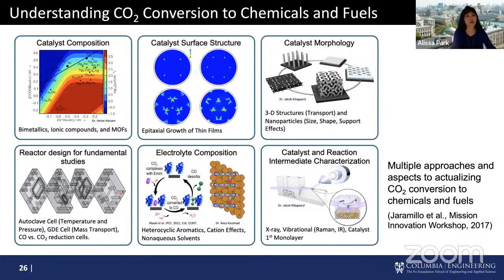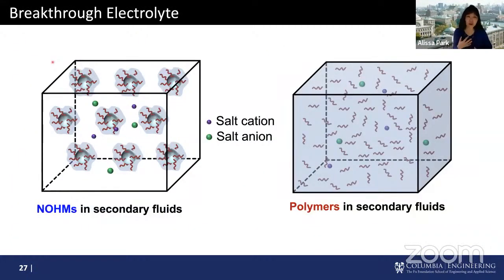catalyst. A lot of my colleagues are working in this area, looking at how to develop new catalysts, catalyst morphology, even reactor systems. But not that many people really focused on electrolyte design. In fact, the CO2 solubility in regular conventional electrolyte is very low. So then you can go to 2 different options. Either you can go to gas diffusion electrode, minimizing all the dissolution issues, or you can make the electrolyte better, increase the solubility of carbon dioxide. That led me to think about what if we use this NOHMs system we developed as additives for electrolyte.